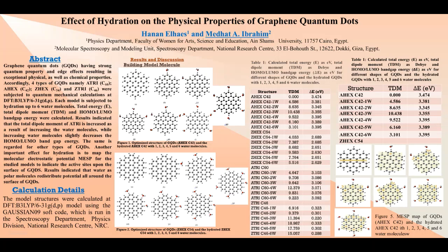Each model is subjected to hydration up to 6 water molecules. Total energy, total dipole moment, and the highest occupied molecular orbital and lowest unoccupied molecular orbital bandgap energy were calculated. Results indicated that the total dipole moment of armchair triangle is increased because of increasing the water molecules, while increasing water molecules slightly decreases the bandgap energy. The same is regarded for other types of GQDs.